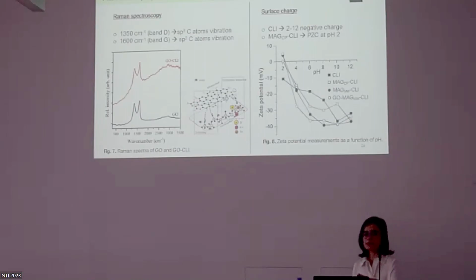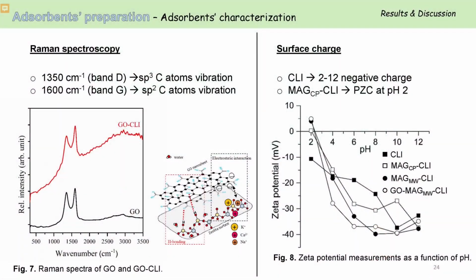Also, to detect and confirm the graphene oxide on the clinoptilolite, Raman spectroscopy was performed. Here is the spectrum of the commercial graphene oxide and the graphene oxide coated on clinoptilolite. It can be seen that the two main bands of graphene oxide are also visible in the spectrum of graphene oxide clinoptilolite, which confirms the graphene oxide on the clinoptilolite surface.